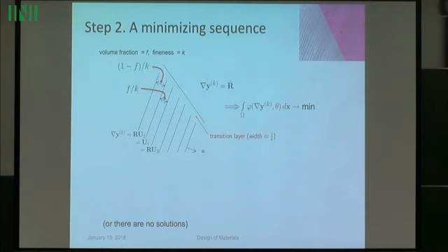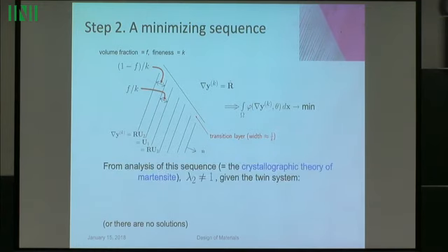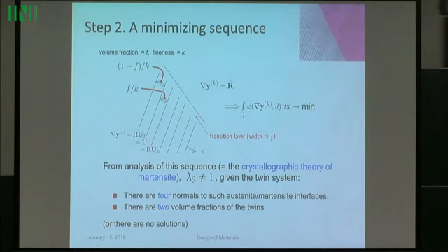But it requires special conditions. As I say, you have to get these things exactly right, and it's quite a rigid calculation. You get 4 normals to this interface. There are 2 possible Fs. I'll tell you a bit more about the calculation later. But it's fairly rigid. And if you take, among the several cases you get where this is possible, one of those cases, it will agree incredibly well with this picture.